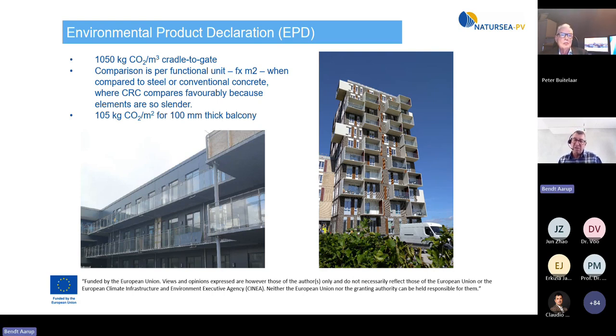But what's interesting is that if you look per functional unit, for instance, square meter of balcony, then because we have very slender elements, the load is not very high, and we're about 30 to 50% better than conventional concrete, and about 25 to 30% better than steel if we look at a balcony. So we have a large advantage of being able to make very slender elements. It also uses less material, so less raw natural resources, less load on the buildings, etc.